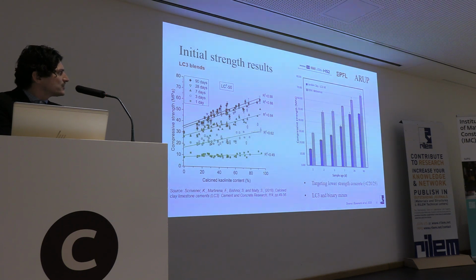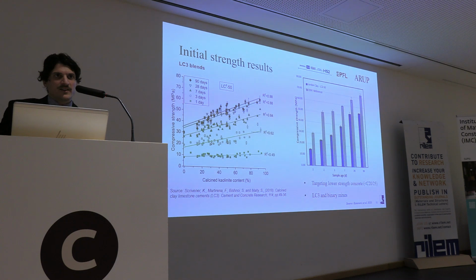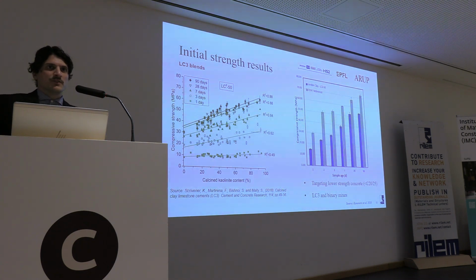We can actually get structural level concrete strength with this kind of initial LC3 assessment. But also, we can investigate binary mixes. And why? Because we generate too much waste clay that has to be transported. If we can use as much of it back in concrete, it will be beneficial from a logistical perspective. So yes, LC3 was a promising technology in terms of the synergistic effects of calcined clay and limestone, but the binary concept was that we use as much of this waste clay as possible in concrete.